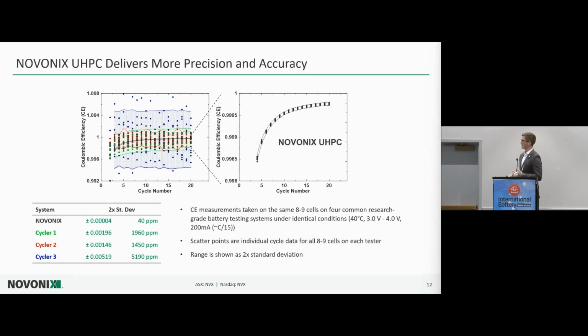So just to highlight what UHPC is capable of, if we line this up with a bunch of other types of cycler equipment that's available and is probably in most labs that people own here, and you throw 8 or 9 identical tier 1 cells on those pieces of equipment and cycle them, you can see these spreads of some of these pieces of equipment. And for the coulombic efficiency measurements on NOVONIX UHPC, the spread is 2 orders of magnitude better than any of these other pieces of equipment. So really we're identifying the actual difference between the cells at this point. Which means, if you want to change your chemistry, an electrolyte, a cathode material, a dopant, we can start to see very accurately, very consistently, repeatably, differences between chemistries that you may not be able to see in just a short number of cycles on other pieces of equipment. And this was the real motivation behind UHPC, something like 15 years ago in Jeff Dahn's lab.